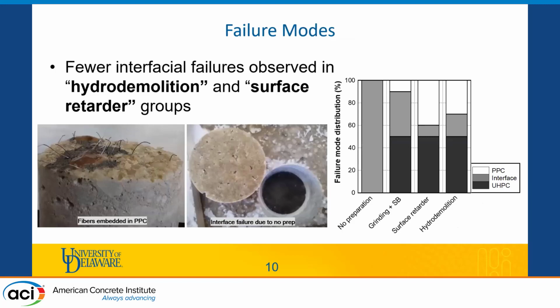So it's true that the hydrodemolition and surface retarder have lower strength compared to the grinding and sandblasting. However, in terms of failure mode, we see fewer interfacial failures for these two methods specifically. For the no-preparation case, all the failures were recorded at the interface, most of them being totally failure at the interface, and those that were between 300 and 400 psi were mixed failure modes. However, the majority of the surface was failure at the interface.